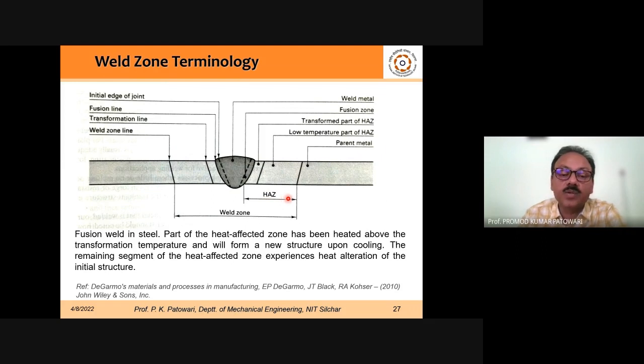And why this heat affected zone? Because when you heat the material and the temperature reaches quite high, and that temperature might be the transformation temperature or the recrystallization temperature, then this material changes its structure. If the material changes its structure, that is not the desired material which we exactly wanted to join. And here you can find there may be some detrimental effect. The material becomes very brittle. Some cracks may be initiated there. So ultimately, there is a chance of failure of the material in this zone even.